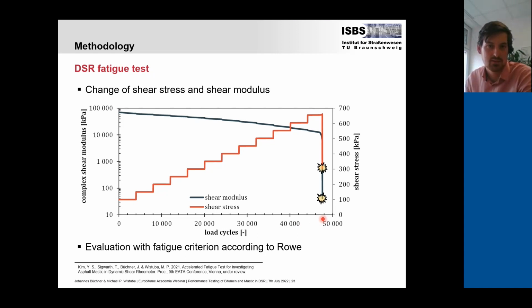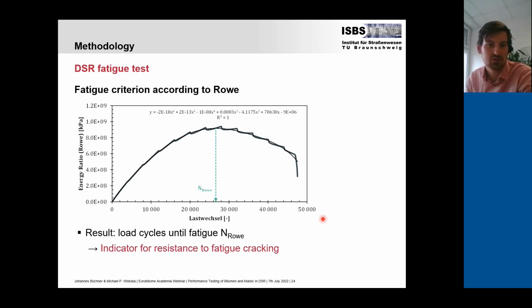We evaluated this test with the fatigue criterion according to Rowe. This is what you can see here. We look at the energy ratio and determine the maximum point of the energy ratio, and the number of load cycles to reach this maximum is the result of the test, as an indicator for resistance to fatigue cracking. Here you can already see we required a polynomial regression, since due to our stepwise increase, we can also see these small peaks, which make it difficult to actually determine the maximum. We already have a solution for this as well, but this is the status from 1 year ago, which was the result of this research project.